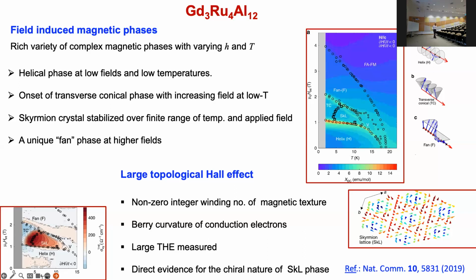And what about transport measurements? The main interest in this compound arose because of the large topological Hall effect that it exhibits. There is a non-zero integer winding number of the magnetic texture because of the skyrmions. This gives rise to a Berry phase for conduction electrons, and that results in a topological Hall effect, which is measured to be large in this material and is direct evidence for the chiral nature of the skyrmion lattice phase.